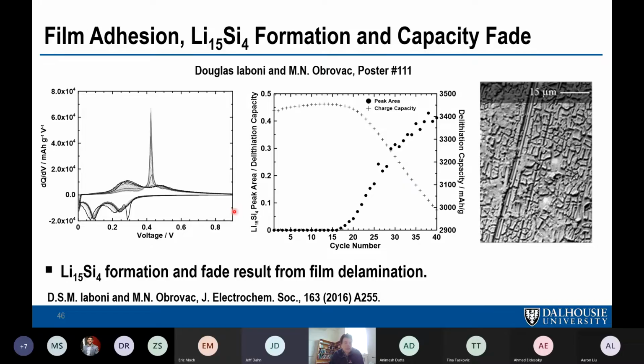If you start out with an alloy having a perfectly being able to lithiate and delithiate in a single phase region, we believe that's the inactive phase suppressing the 15-4 formation because of this stress voltage coupling. If you start seeing growth of the 15-4 phase during cycling of the alloy, that typically means the silicon phase is becoming disconnected from the inactive phase, and that usually means that you're going to start to see fade.